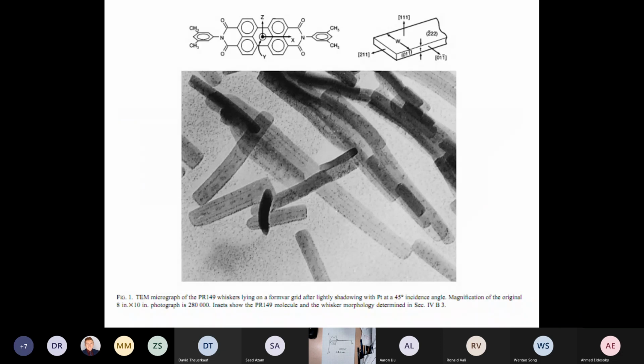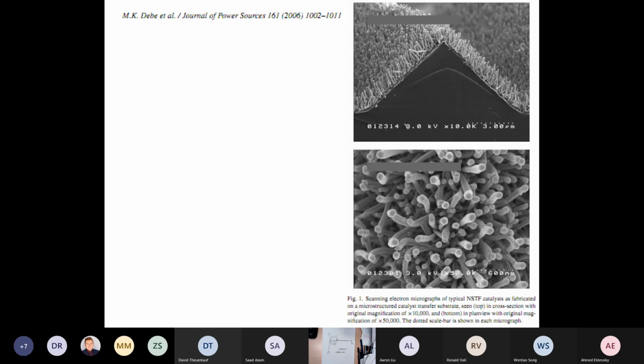And then they realized they could make a catalyst support out of this. So this is a SEM image of what they made. So let me explain this to you. So you can see the scale bar, 3 micron. So each of these little whiskers is about 750 nanometers long. And it's been deposited on a microstructured polyimide support that looks like a repeating set of triangles.